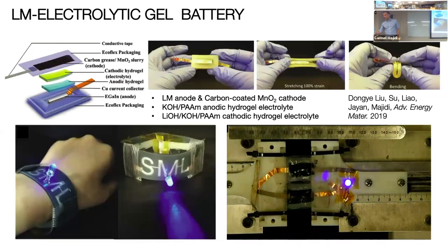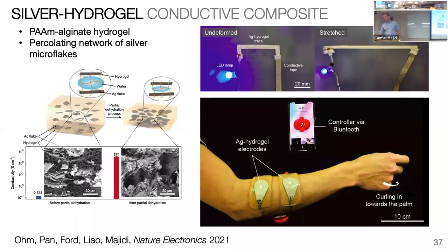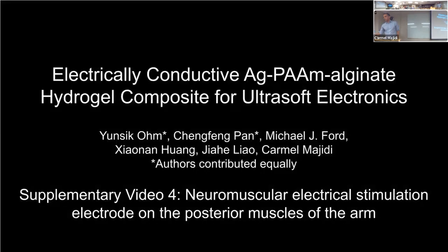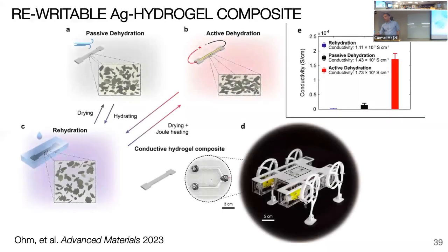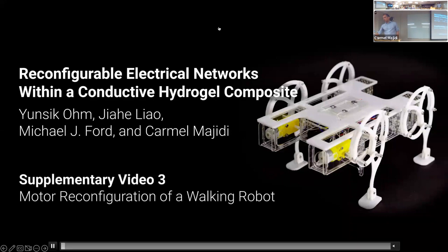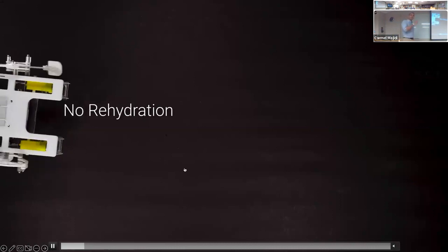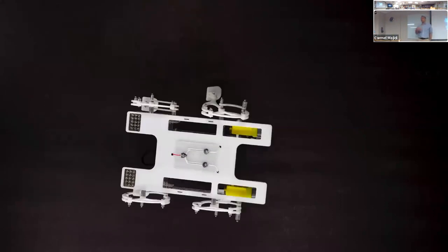Bottom line here is that there's cool stuff we can do in making soft batteries with gels. We can also make systems that are even more compatible with the body, if we want to make soft bioelectrodes when we use gels as the matrix material. I'll let this video run a little bit. This is a fun example of using gels and actually reconfiguring their conductivity. The nice thing about gels, as opposed to a silicone rubber as our matrix material, is that we can use hydration and dehydration to increase or decrease the conductivity in a reversible way.